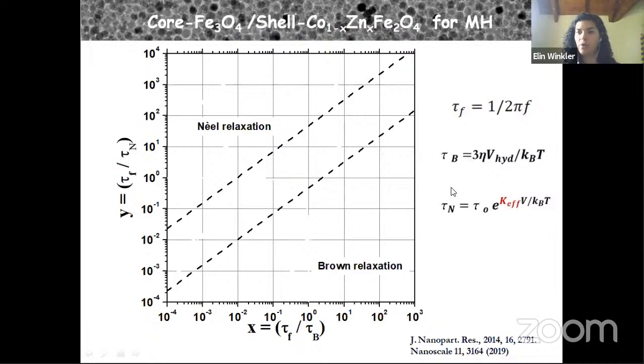Here we have three important times. The Neel relaxation time depends on the magnetic parameters, and we know all these values. The Brown relaxation depends on the viscosity and the volume of the nanoparticles. And this is the characteristic time of the hyperthermia experiment, given by the frequency of the AC field. So we just compare these times. And this graph helps us to see if Brown relaxation is the dominant one, the smaller one, which is this zone of the graph, or if the Neel relaxation is the dominant one.